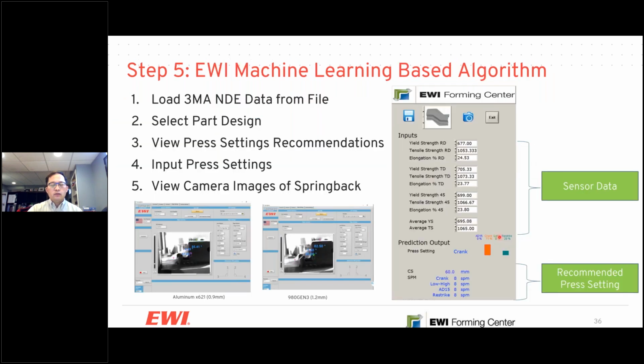And then finally, we input that data into our control algorithm, and the control algorithm reports the input data from the sensors and also recommends the press setting based on the data. Now, we have a handful of data. We are not only using a few data points; we ran at least 300-400 data points in our testing, meaning 300-500 experiments to create the database.